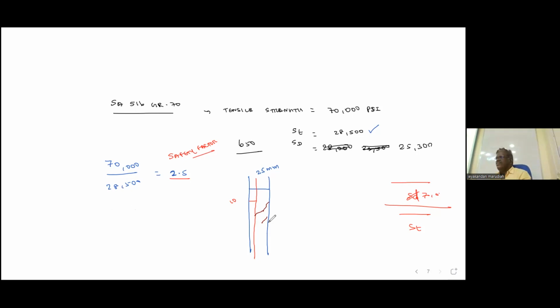Or a defect: we want to run a tank with a defect, it can be a crack, a reduction in thickness, lamination, or any other problem. We have a problem which is generally not acceptable, but we are analyzing whether we can run with the problem for some particular period. That is called fitness for service analysis. How does fitness for service analysis work on the safety factor? We are utilizing the safety factor because most structures have excess thickness. So we are using the extra thickness. I hope you understand.